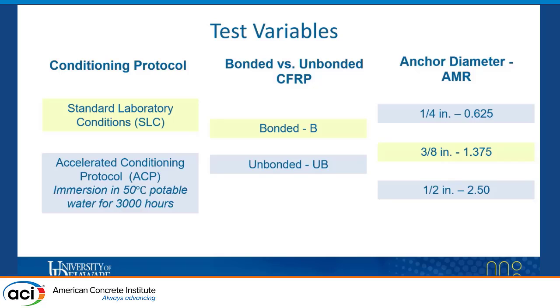What I have next to these anchor diameters is the AMR, which stands for anchor material ratio, which is the ratio of the cross-sectional area of the carbon fiber splay anchor to the area of the flexural strip in which it's anchoring. The reason we selected the anchor diameters that we have here is because existing research has shown that when an AMR of 2 or greater is used, you can obtain strip fracture. So we wanted to observe AMRs that were less than 2 as well as greater than 2.